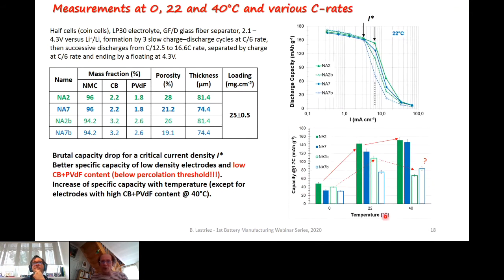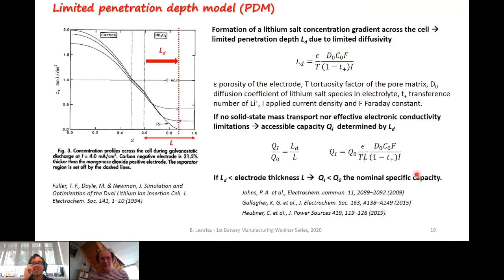So now we can observe the results as a function of the temperature, 0, 22, and 40 degrees C. As expected, at least for Na2 and Na7, we observe a significant improvement of the capacity at 1.7 C, which corresponds here to this vertical. So big improvement with increase of the temperature. This is also observed for the electrodes with the higher amount of CB+PVdF between 0 and 22, but then, fairly surprisingly, unexpectedly, you observe nearly a leveling of the performance for Na7b or a decrease for Na2b. I'll come back to this later.